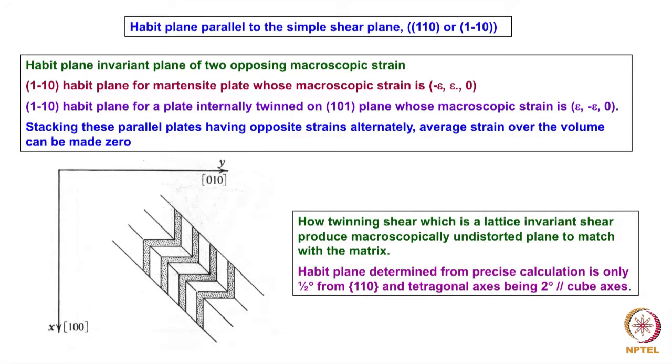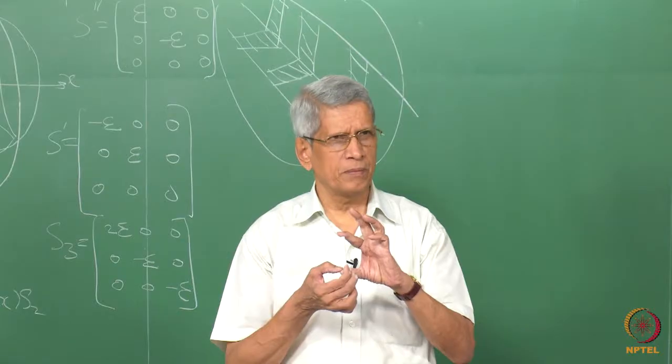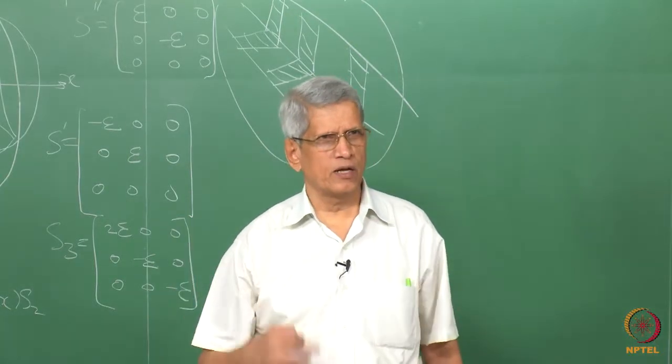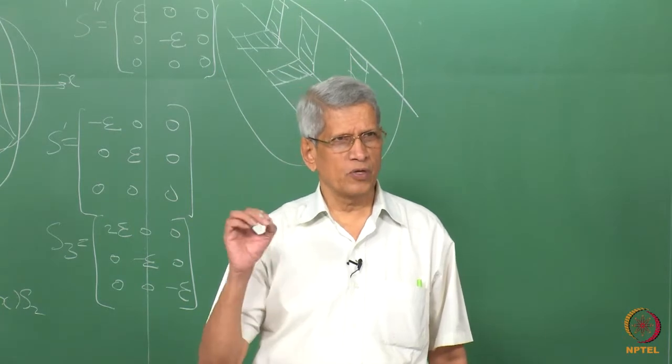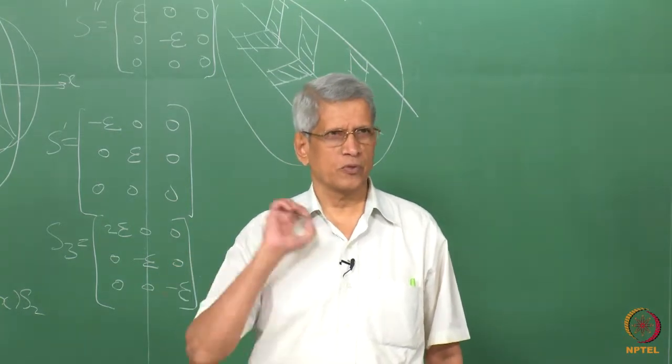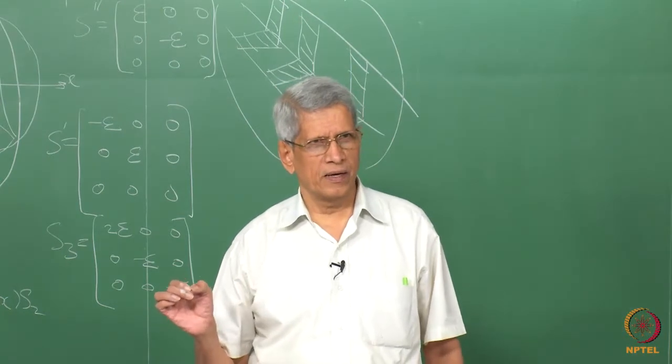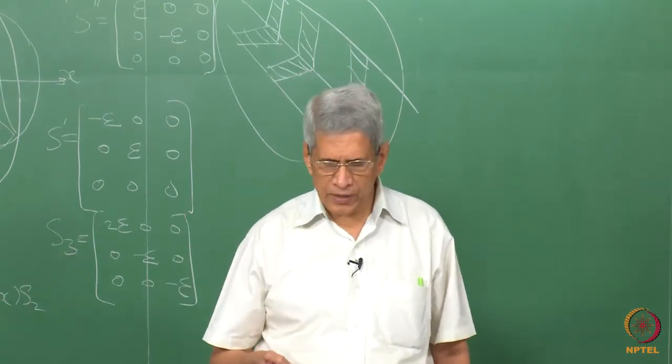You see that again the third variant comes like this if it continues like this. These are all essentially a plate type of Martensitic transformation. And since there is a small tetragonal distortion, some of the tetragonal axes here will be rotated by a very small angle. Even that angle we can calculate, knowing how much the tetragonal distortion is. So when we find out the orientation relationship, this much rotation also will be seen from the position of the diffraction spots corresponding to matrix and the martensite.